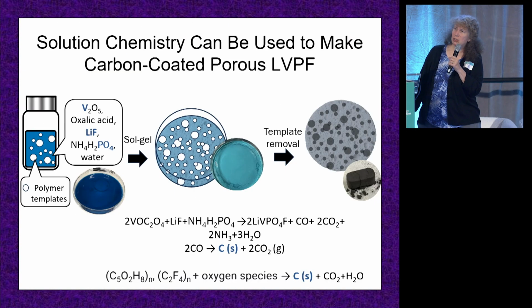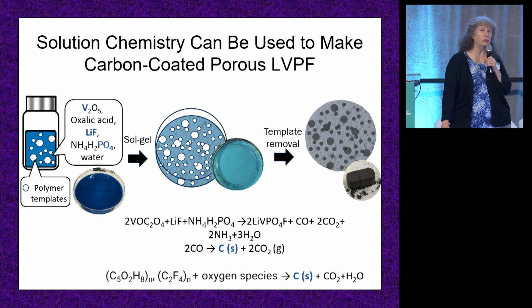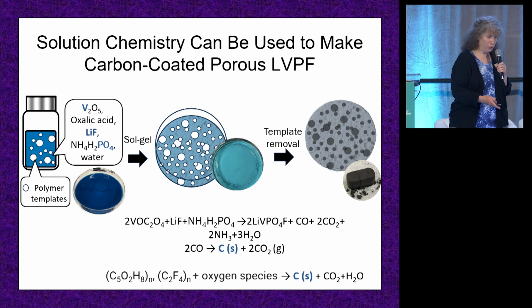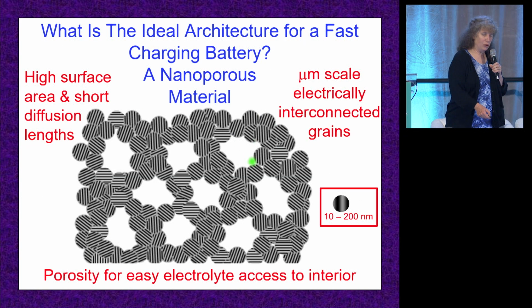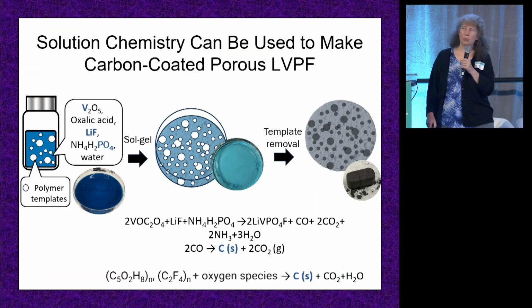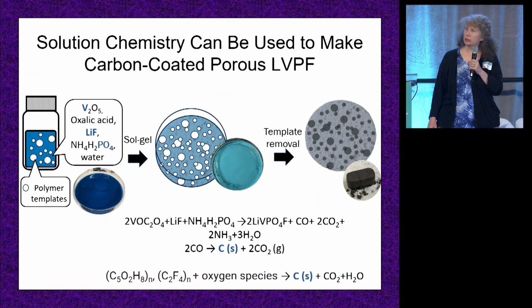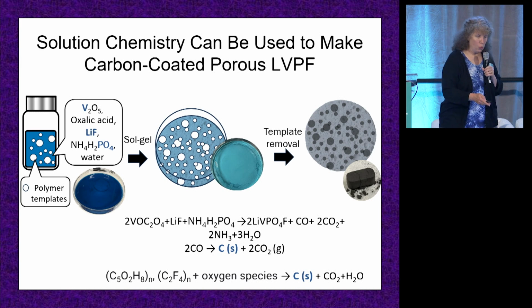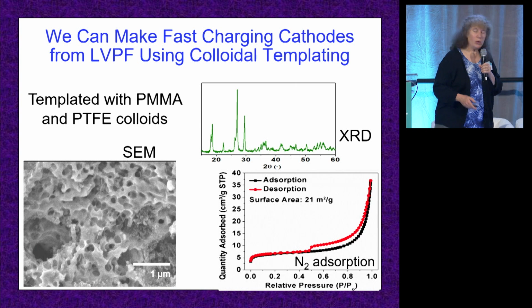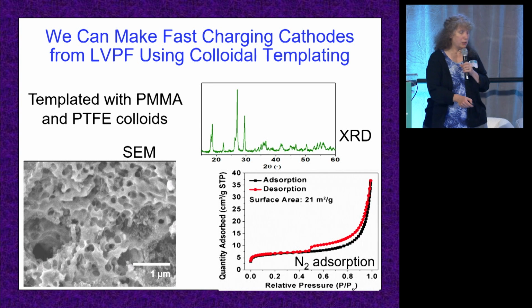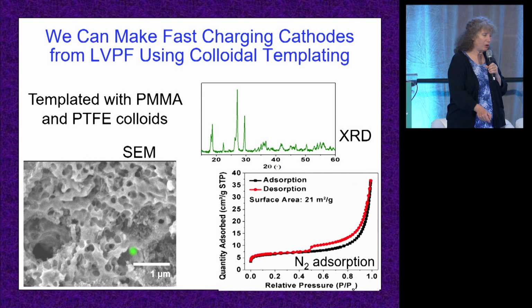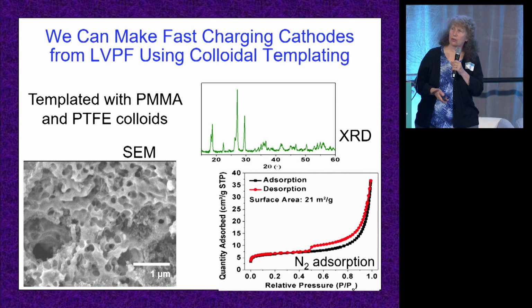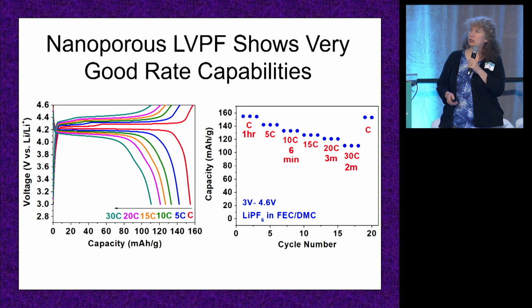Okay, so we have developed methods to make this LVPF by low-cost solution phase methods where we take a polymer and use this to make these holes. So we need a method to make these holes. And the method that we use is we take a polymer and we co-assemble it with precursors to the material. We do that in solution. So we just simply mix things, let them gel, and then heat them. We degrade the polymer and it leaves behind holes. Okay, so we did this actually a little bit ago. We made nanoporous lithium vanadium fluorophosphate. This is an electron micrograph image. You can see all the little holes. We can characterize it. It's good quality material. And it charges quite quickly.